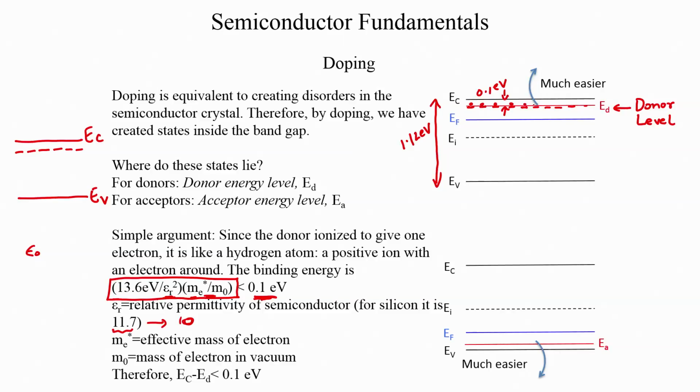So this was the charge neutral species, at let us say temperature T equal to 0. But the moment the temperature increased a little, these electrons gained enough energy, they gained this 0.1 electron volt energy to snap away from the donor and to get into the conduction band of the lattice.